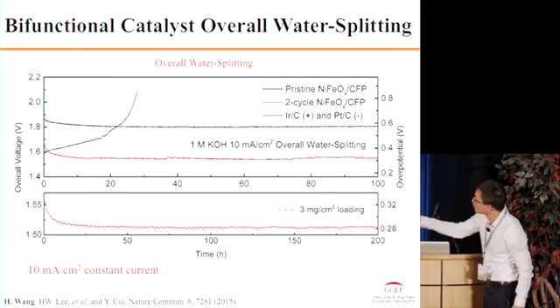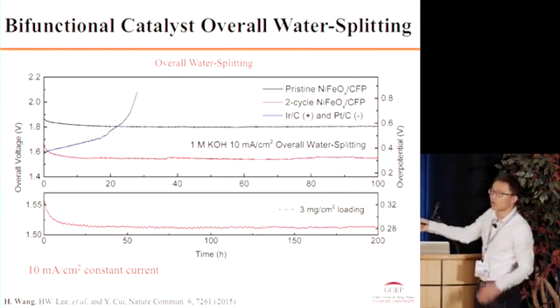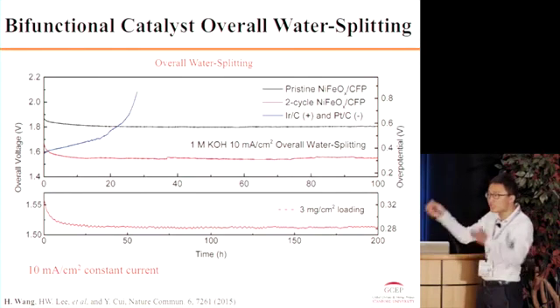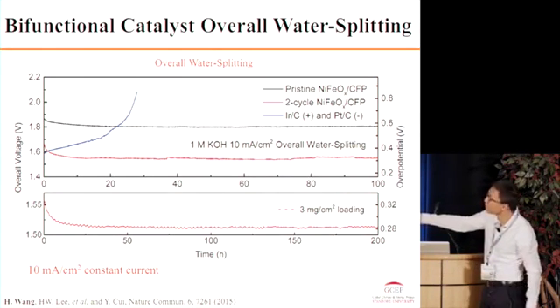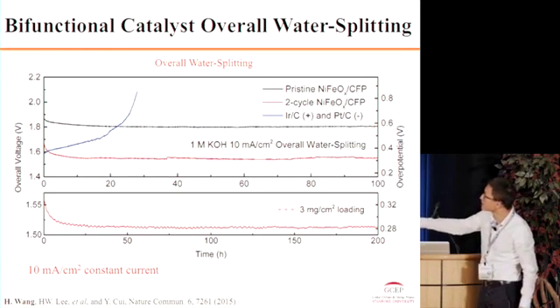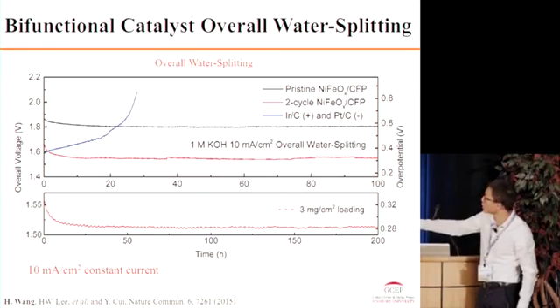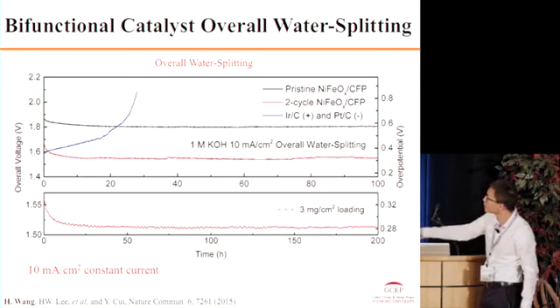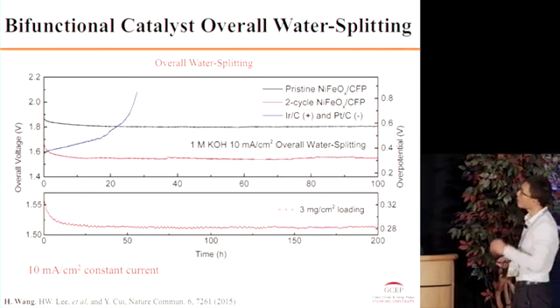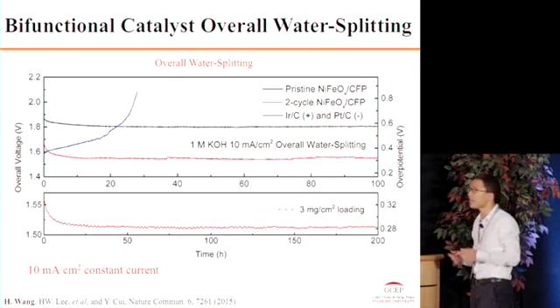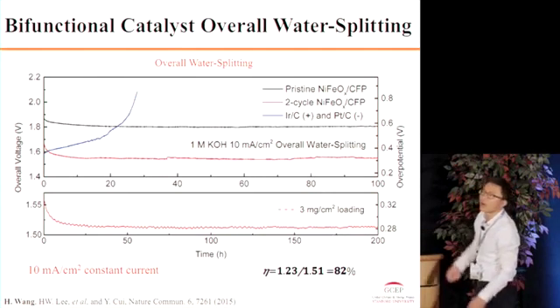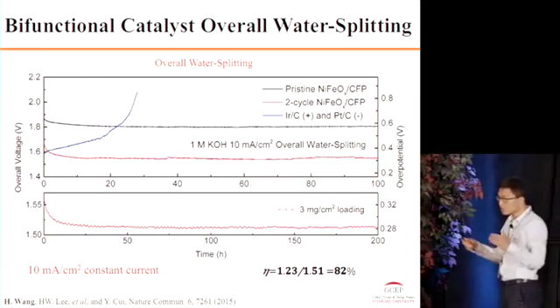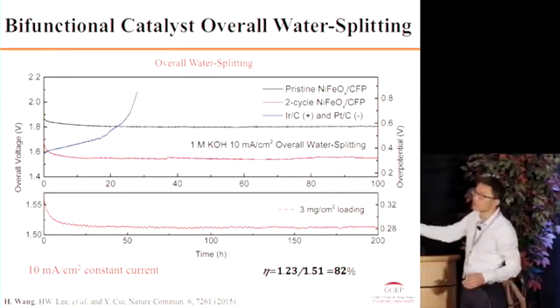As we can see, we hold a 10 milliamp per centimeter square current and test the voltage needed to drive this current. We combine the iridium, which is the OER catalyst, and platinum, the HER catalyst, together. As time continues, the voltage required to drive the 10 milliamp increases continuously. But for our bifunctional single catalyst, the voltage is stabilized. And when you increase the loading a little bit, you can achieve this 10 milliamp at only 1.51 volts for 200 hours without any degradation. This gives us a very high efficiency, 82% of the electricity converted to hydrogen. That is pretty high. And the stability is really good.